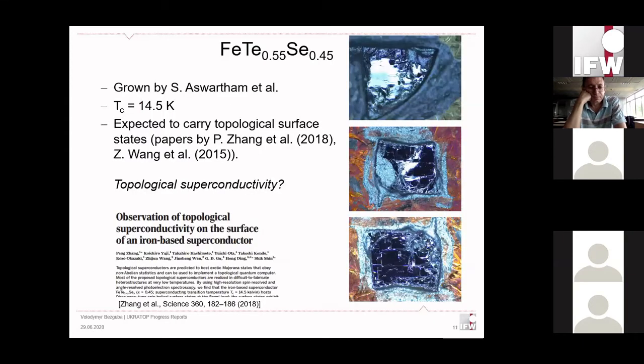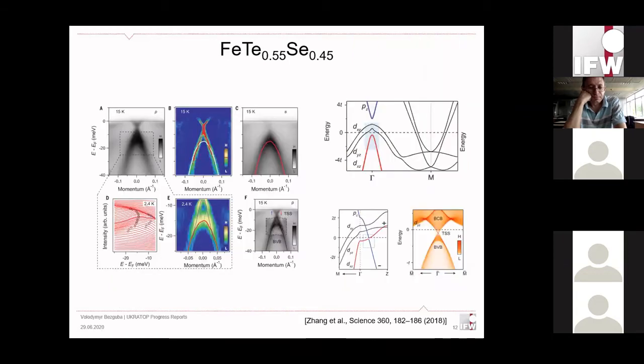The group of P. Zhang, who published their first paper in 2018, reported seeing this Dirac cone in their spectra. This is one polarization of the light, this is another polarization of the light, and they did their measurements with a 7 eV laser. They claim this to be a Dirac cone, and it aligns nicely with their calculations, which you can see on the right. The pz band crosses dyz and dxy and even dxz. So this part opens the inverted gap, and in it topological surface states emerge.